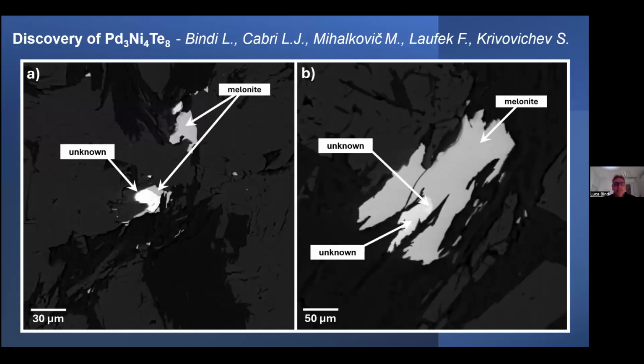And indeed, recently, we described, together with some friends, a new mineral. This mineral was found associated to melonite, which is an important nickel telluride, quite common. And we discovered this phase, which is enriched in palladium. You can see the bright grains.